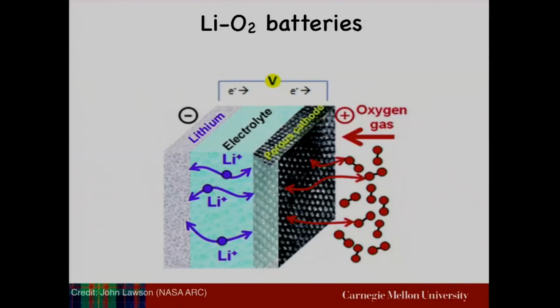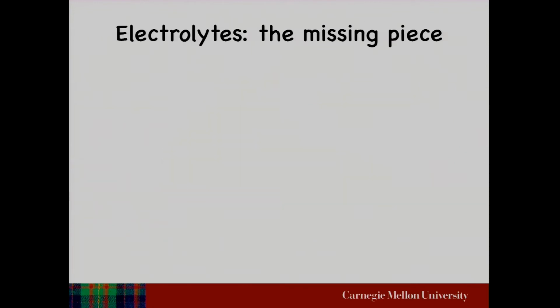All right, so how does a lithium oxygen battery work? It has a lithium metal anode, like we discussed last time, and a liquid electrolyte and some sort of porous material, and oxygen flows in from the tank and the lithium and the oxygen react to form lithium peroxide, which is a compound whose chemical energy is what you release as voltage in the cell. Now, it turns out that lithium peroxide is one of the most reactive compounds known. And so liquid electrolytes tend to react with the product formed, and so these batteries don't cycle very many cycles. And so the electrolytes in this case are the missing piece to enable lithium oxygen batteries.